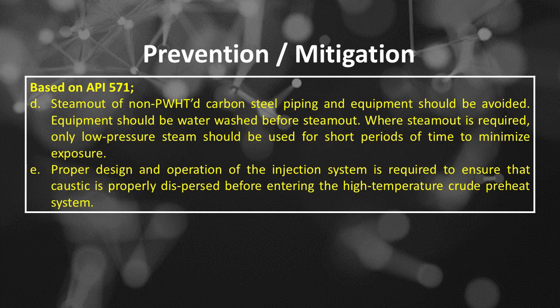Number D, steam out of non-PWHT'd carbon steel piping and equipment should be avoided. Equipment should be water washed before steam out. Where steam out is required, only low-pressure steam should be used for short periods of time to minimize exposure. Number E, proper design and operation of the injection system is required to ensure that caustic is properly dispersed before entering the high-temperature crude preheat system.